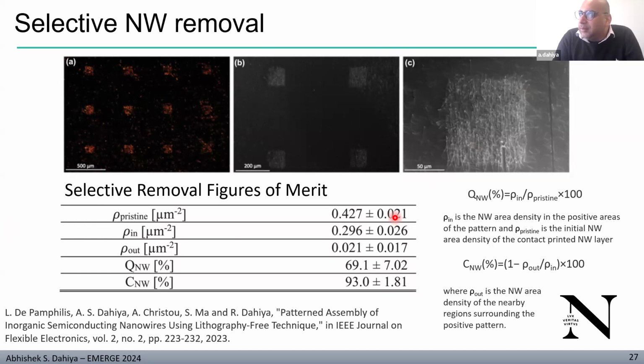I think the company claims around 1 micrometer, but yes, it can go lower with very proper optimization. We have not been able to achieve that. We have achieved up to 1 micrometer line, as well as the pitch, which is not for a transistor but for temperature sensor work. On vanadium pentoxide nanowires, we have done that. Yes, it has potential, and it's a good tool for R&D, as you can just change the design on the go.